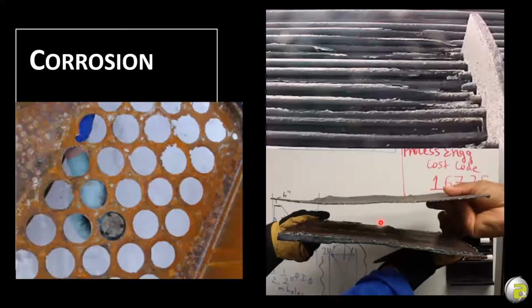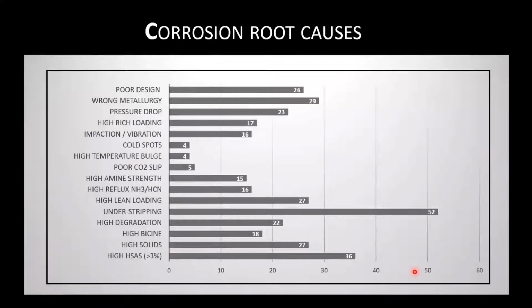A heat-stable salt is whenever I get a stronger acid than H2S or CO2 into my process, it reacts with the amine and it makes a strong salt, and the salt is non-regenerable. So we say it's heat stable. We can't break that salt apart. So it builds up, and because we're retaining an acid, it drops the pH of the fluid and the acids attack the steel. So many different ways that we can get corrosion.